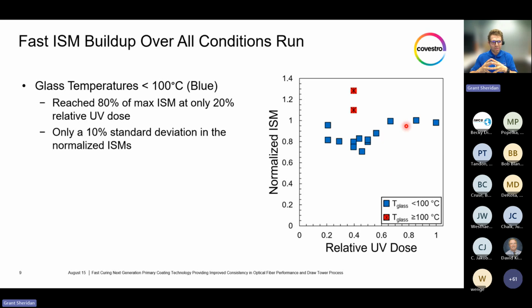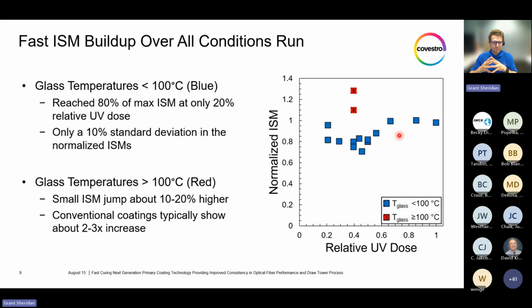Additionally, we could see the improved consistency, as there's only about a 10% standard deviation in the normalized in situ modulus over all relative UV doses. Now, when we look at the high glass temperatures above 100 degrees C, we do see a small 10-20% jump in the in situ modulus relative to those below 100 degrees C. However, we believe conventional coatings typically show a 2-3-fold increase with increasing temperature. So these next generation coatings further show more temperature stability and more insensitivity to the glass fiber temperature, in addition to the coating thickness shown before.